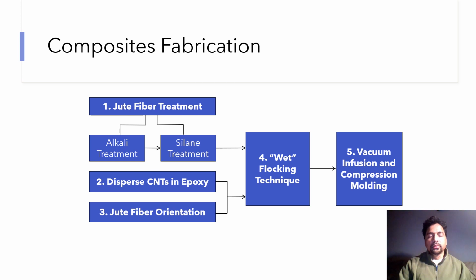In addition, we need to do a good dispersion of carbon nanotubes in the epoxy matrix. Otherwise, we cannot generate a good conductive network in the system. We also wanted to see the effect of jute fiber orientation, such as a unidirectional composite as well as a cross-ply composite, which is a 0/90 composite. In this part of the study, we wanted to investigate the effect of jute fiber orientation on the conductive network. As I mentioned, we employed a wet flocking technique to reinforce short carbon fibers between the jute laminates. Then we employed the standard vacuum infusion process along with compression molding to fabricate these composites. The reason we employed both techniques is to generate at least a 60% volume fraction of jute fabric in the composite.